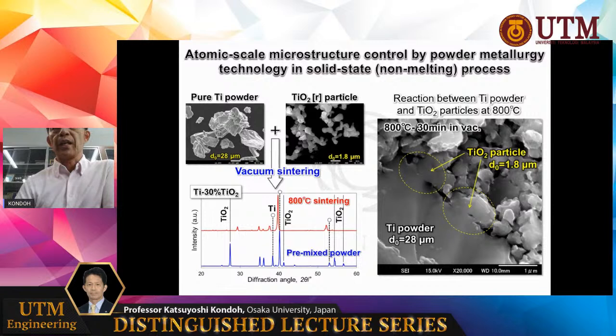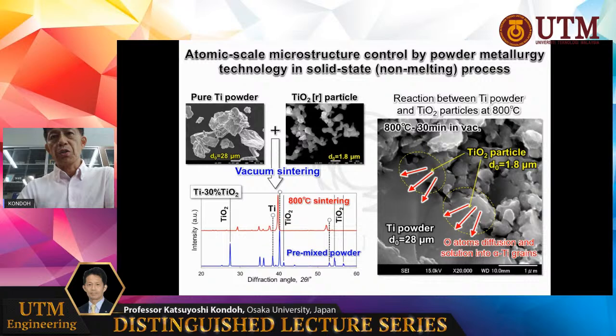This fine particle is TiO2, rutile particles, and the large one is titanium powder. At the interface, you can see TiO2 reacted with titanium powder, shown here. And during the sintering at, for example, 800 degrees C, TiO2 particles decompose and oxygen atoms originating from TiO2 diffuse into the titanium powder and completely dissolve into the alpha titanium grains. So this is a very simple process to obtain titanium materials with a high concentration of oxygen atoms.